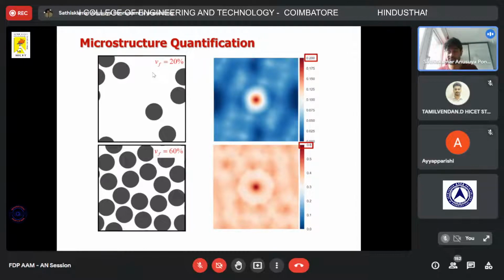The two-point correlation function is basically what you see on the bottom right. Again, the peak value is the volume fraction, that is 60%. But what is important to understand here is that this two-point correlation function basically represents your microstructure. And why are we doing it?